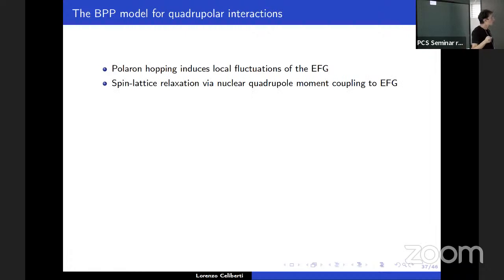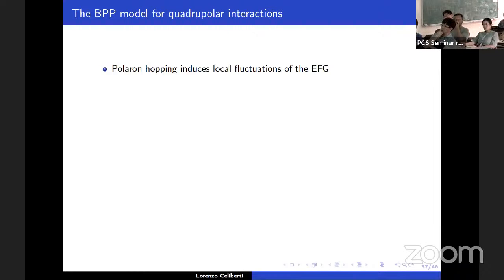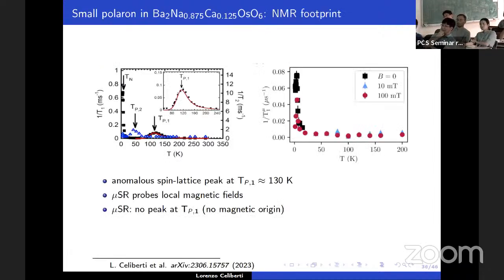You only show the 1/T1. What about the shift around the 100? In the NMR, the shift even more. I don't know about the shift. The shift is directly related to the magnetic susceptibility in the magnetic system. I don't know about that because some data are still under elaboration, these experiments. So far I only got this data.